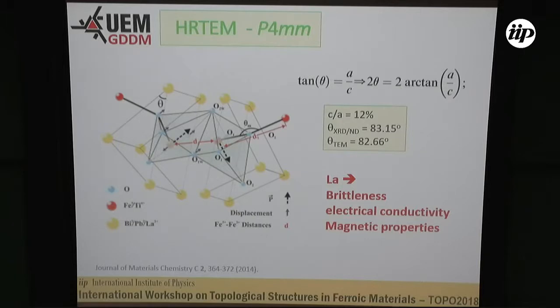What is the consequence? If you have a big or high tetragonality, your sample usually is more brittle. Those who process ceramics know that very tetragonal ceramics are usually more brittle. If you change this lanthanum concentration, you tend to diminish this tetragonality factor, and the brittleness goes down. The electrical conductivity can be changed once you change the distance between oxygens and iron atoms in this region. Also the magnetic properties, because the super exchange is in this region. If you change this distance, you can affect this angle of the super exchange, and also the distance between the two oxygens or two iron atoms, in this case, that are doing the super exchange.